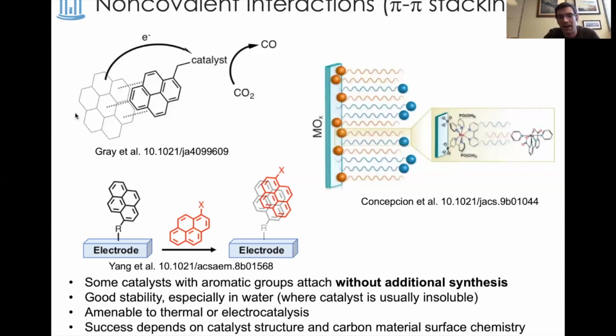Generally, these have been done on graphenes or carbon nanotubes as the materials of support. More recently, there have been efforts that modify the surface to enable these attachments non-covalently, such as putting a pyrene group on the electrode surface or on a material surface, and then having another pyrene group on the catalyst and allowing them to come together. Or in this example, that's from Jenny Yang's group. In this example from Javier Concepcion's group, using long chain alkanes to have hydrophobic interactions that put the catalyst on the surface of a metal oxide.